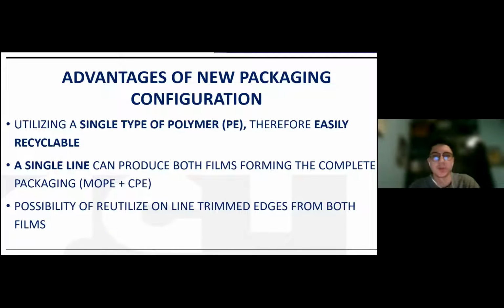In fact, the advantage of this new packaging configuration is the utilizing of a single type of polymer, the PE, easily recyclable, single line that can produce both films, forming the complete packaging, because with the same line you can produce the CPE and the MOPE by utilizing the MDO unit, and the possibility of reutilizing online trim and edge from both films. For sure, this is one of the best points and the best key factor, because in our lines and in cast lines, you can utilize 100% of the trim in line and utilize it as virgin material.